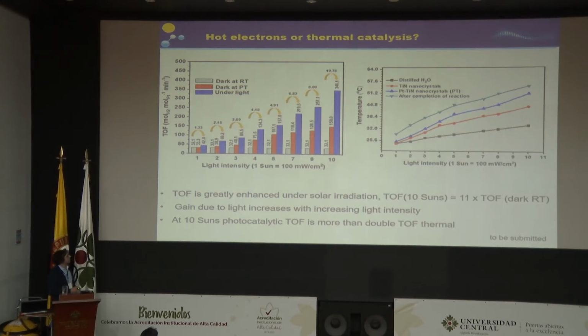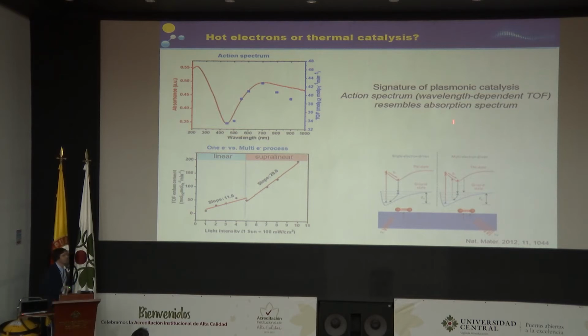This is to say that at 10 suns, for example, the pure hot electron activity for hydrogen generation is 2 times more than the thermal contribution with this hybrid catalyst. Here are just some mechanistic insights. If we do the wavelength-dependent reaction, using not solar light but one wavelength, we achieve a rate of hydrogen production that follows the surface plasmon resonance. This is a kind of signature of the nature of our reaction. And we can also see that we observe a change of electron regime by using different light intensity.